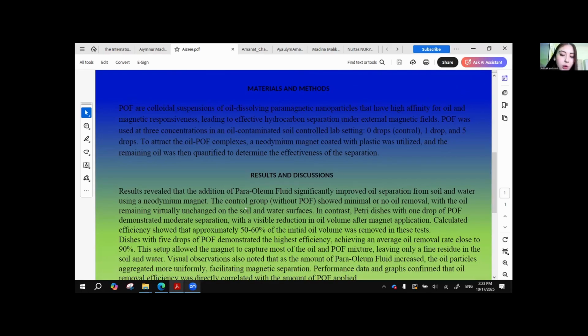So in our experiment, we tested 3 different concentrations of POF, 0, 1, and 5 drops in oil-contaminated soil samples. Using a magnet, we measured how much oil could be removed, and the results were remarkable. The control group without POF showed almost no oil removal, but with just 1 drop, we achieved around 50 to 60% efficiency, and with 5 drops, the oil removal rate reached about 90%, leaving only small traces behind. So the more POF was used, the better and cleaner the magnetic separation became.